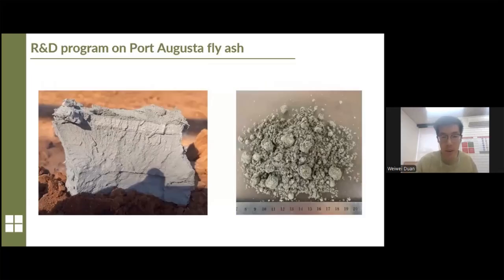That's also a photo of the fly ash we took from the ground. We can see that the top one is coarse particles, and there is a compacted layer with finer fly ash, and that is the typical particle size of the fly ash. And that is the photo of the fly ash we took back to the lab. We put all these samples in the truck and travel back to the lab. That is what it looks like.